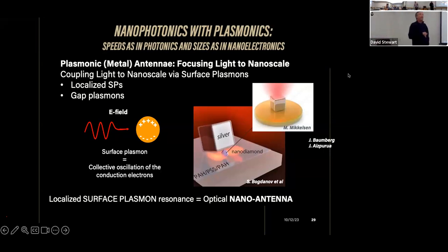If I have a metal particle, let's say 10 nanometers in size, and electrons are displaced, let's say, to this side of the surface, then clearly there would be a restoring force. The electrons will start to bounce up and down with a frequency dependent on the shape and size of this particle, but largely on the shape, because the restoring force depends on this. That's the so-called surface plasmon resonance. The wavelengths could be much, much larger, but all the energy would be concentrated here. That's the idea of the localized surface plasmon.